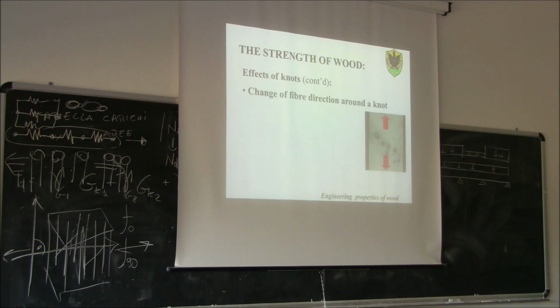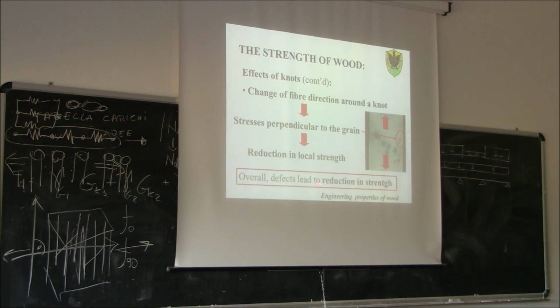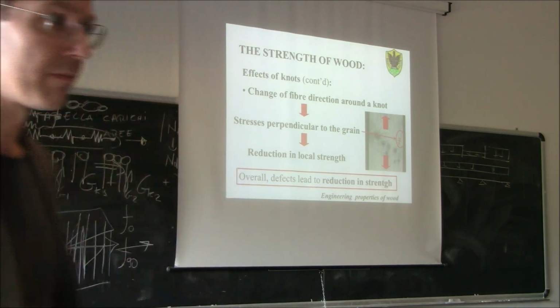And then something that some of you told us before, also the knots are always coupled with some grain deviation. Because you can see here that the fibers have to deviate, and we have some stresses perpendicular to the grain. So overall, defects lead to reduction in strength. We need to keep in mind, it's a very simple conclusion: if we have knots, we will get worse properties compared to the same material without the knots. Clear?